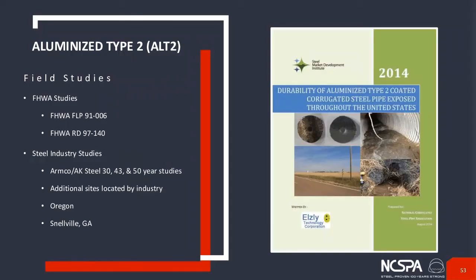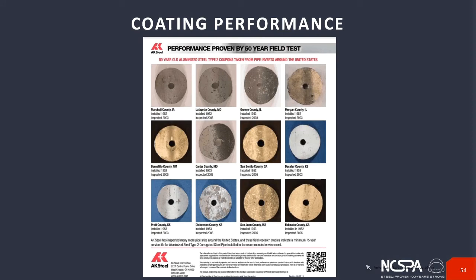Now, aluminized. Aluminized has been studied pretty extensively in and of itself for about 50 years, almost 60 now. Initially, there were a couple of studies done by Federal Highways back in 91 and 97 that looked at a number of installations around the country. Armco and AK had been doing somewhat parallel studies at 30, 43, and 50-year intervals to look at some other sites. These sites amounted to probably 75 or 80 installations, and core samples were taken.